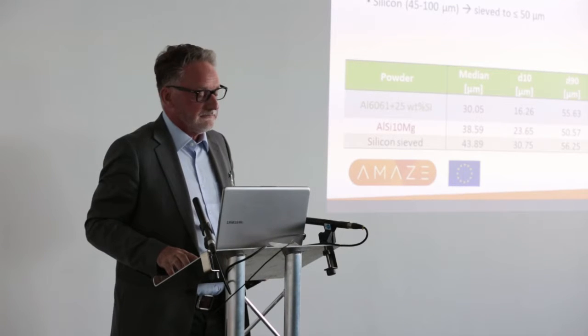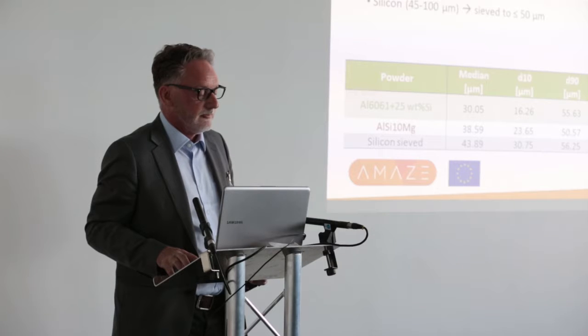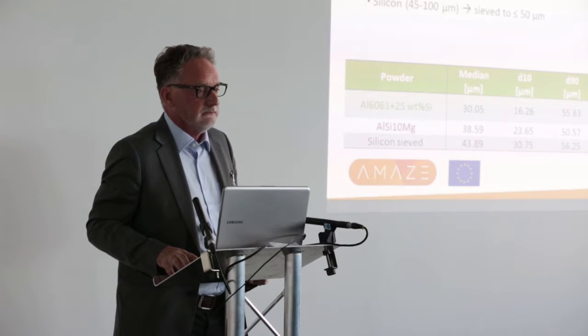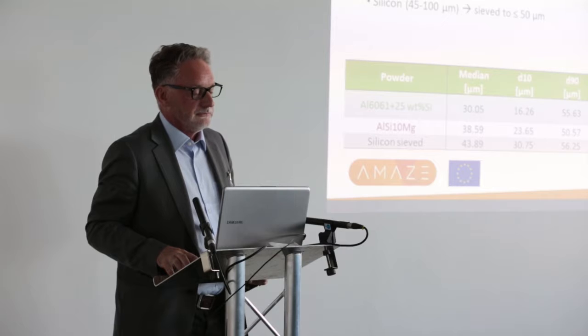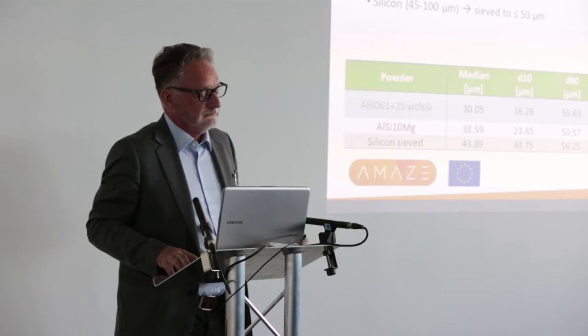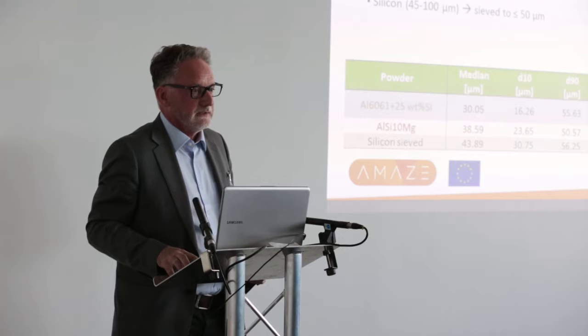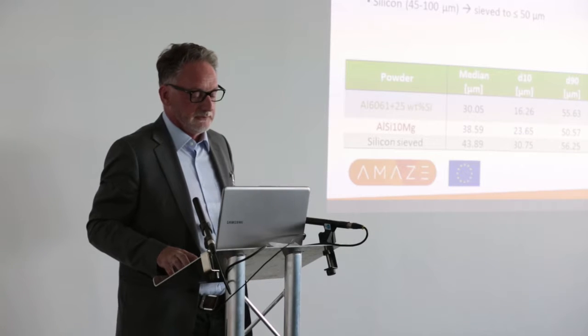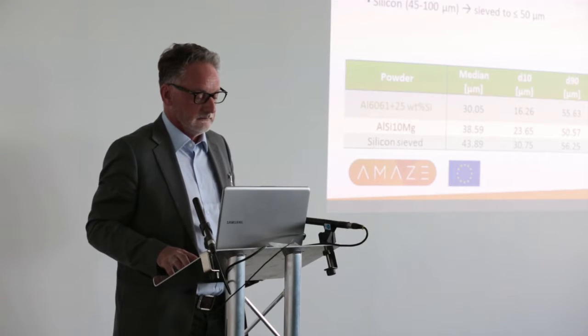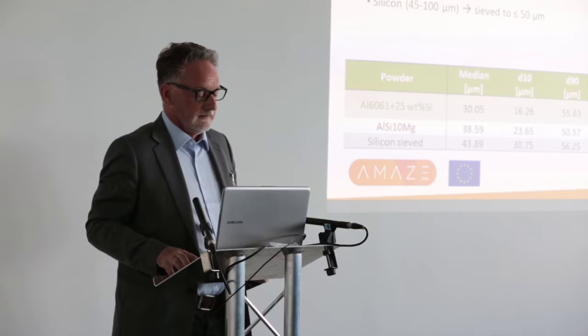So the materials we had were gas atomized by TLS in Germany. We had them pre-alloyed, some aluminium 6061 with 25% weight silicon. So that material was pre-alloyed. Then we had our standard aluminium silicon 10, which is produced by them, and then they produced some silicon, which was initially in the 45 to 100 micron range, but then we sieved that to 50 microns. So we almost had mono-sized silicon that we were using in the project. And you can see the median size of the powders was typical for laser beam processing in the 30 to 45.